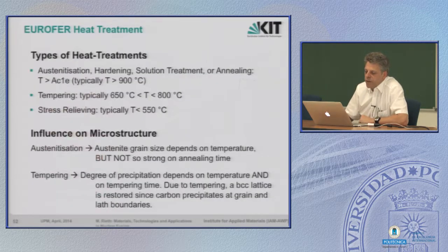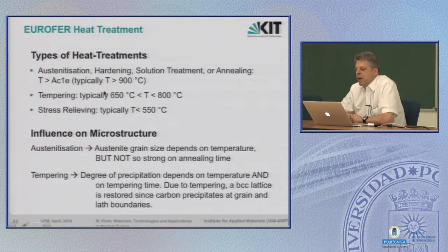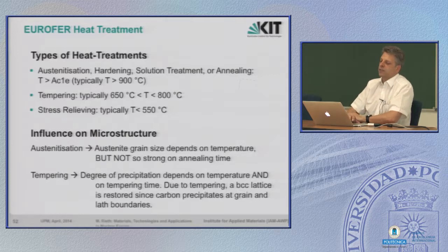That's a summary of the treatment. We have already seen this. That's austenitization or solution treatment. That's tempering. Solution treatment for Eurofer has to be performed above 900°C. Typically, it's around 1000°C. The tempering, which performs the softening again of the martensitic phase, happens in the range of 650 to 800°C, but typically it's 750 or near this value in the Eurofer, and stress relieving typically takes place below 550°C.